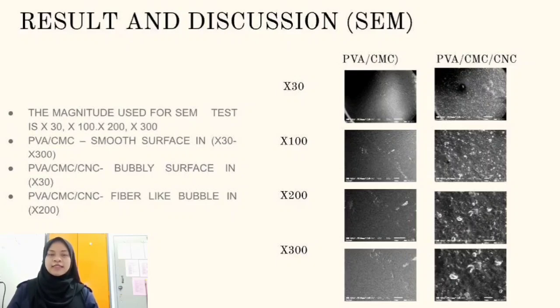The SEM test is used to test sample 2 and sample 4. Sample 2 is the PVA plus CMC blend film. Sample 4 is the PVA plus CMC plus CNC blend film. The magnifications used for the SEM test are 30, 100, 200 and 300. The PVA plus CMC blend film shows a smooth surface morphology, different from the PVA plus CMC plus CNC blend film, which shows a higher roughness surface morphology. The observation shows that PVA and CNC are incompatible as two different constituents. The smooth surface morphology film has better compatibility than the higher roughness blend film.